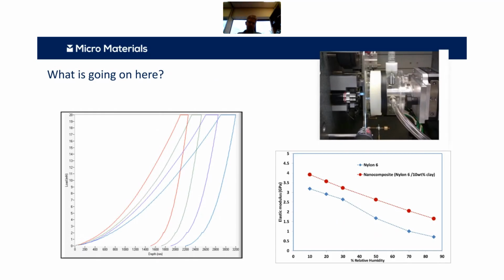Nylon essentially is plasticized by small organics and also by water molecules. So if you want to design this type of test, the best way is to dry it out and then introduce humidity, moisture, into that cell gradually rather than do it the other way around, because studies have shown it takes the best part of 10 times longer to get the water out than to get the water in. So you can study these things. What we can see as well with this application is that there is enhanced stiffness for the nanocomposite over the virgin polymer, but also that improvement in stiffness as a percentage is much better at these high humidities. So that's useful for design purposes again.